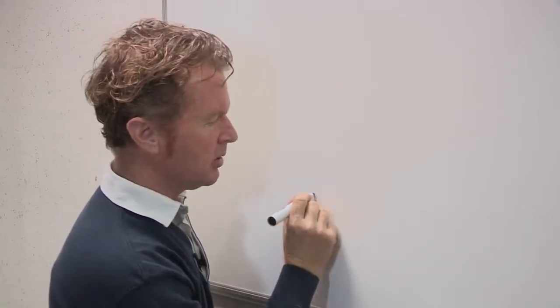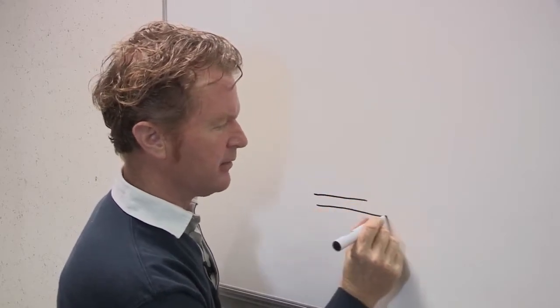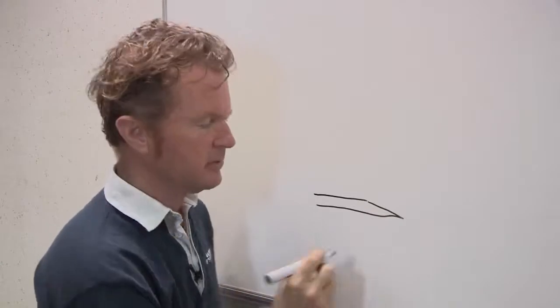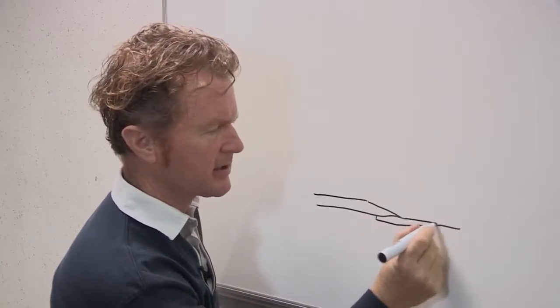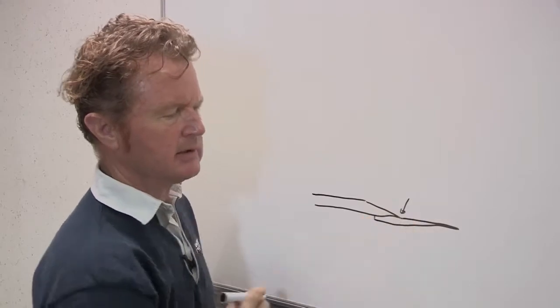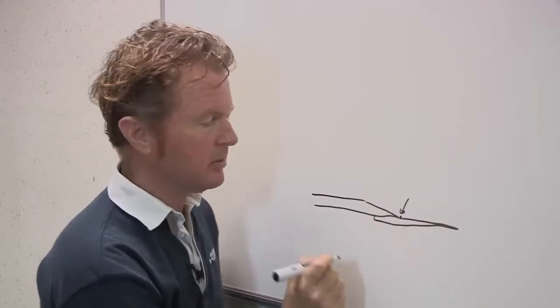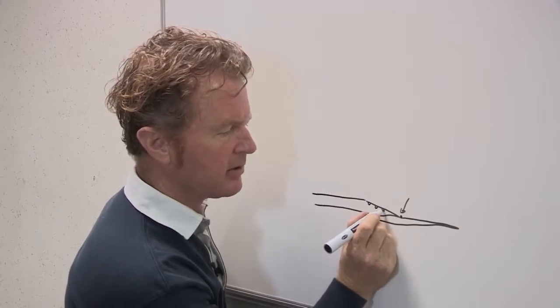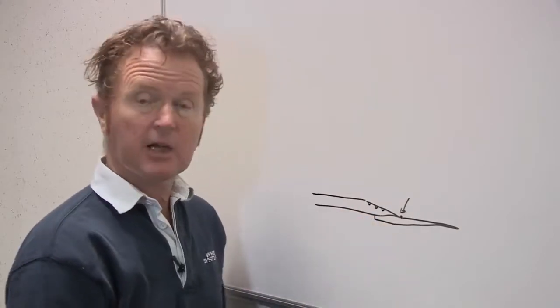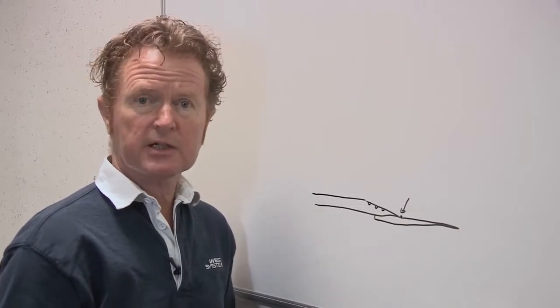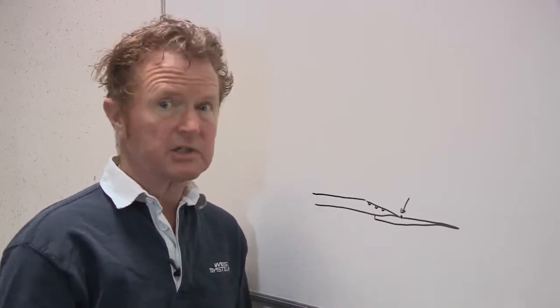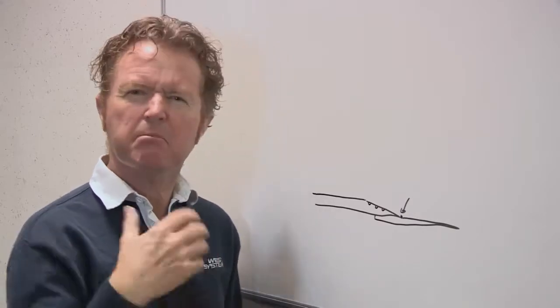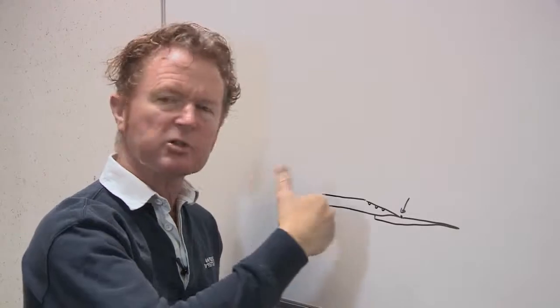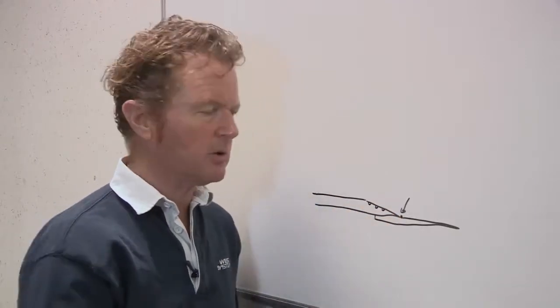Back to some theory. Very small point, but a very important point, is to make sure that you've filled the very edge of your bevel. Where the backing plate meets the bevel, at this point here, you can actually have a small air bubble. You might also find that there are air bubbles in the existing laminate. The perfect thing to fill these with is West System epoxy mixed with West System 406 colloidal silica to a kind of mayonnaise consistency, one that's suitable for brushing. You can use a small glue brush to apply this.